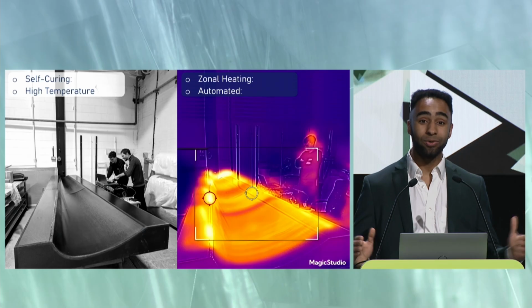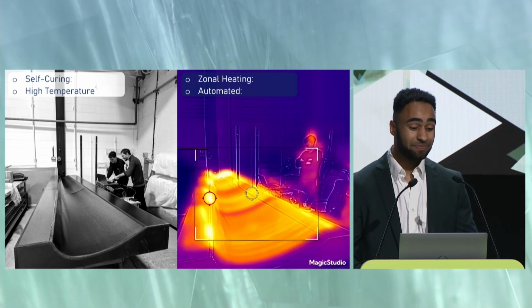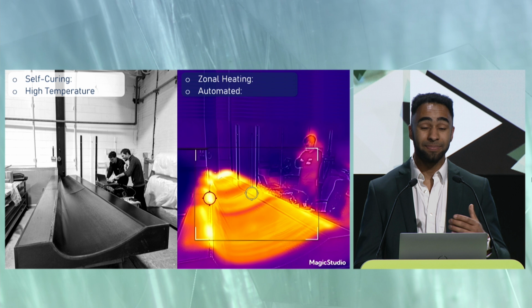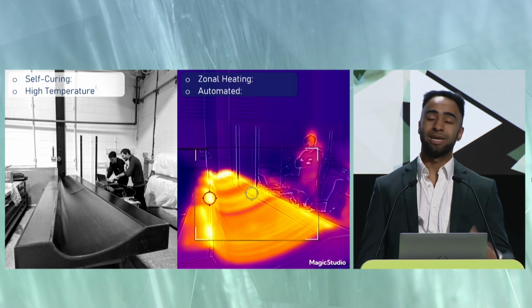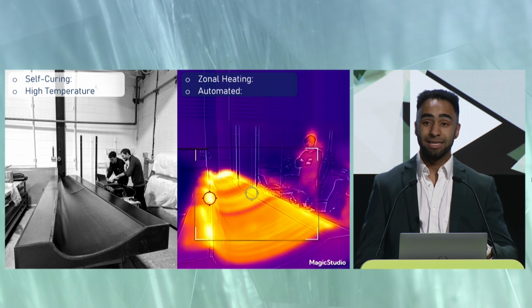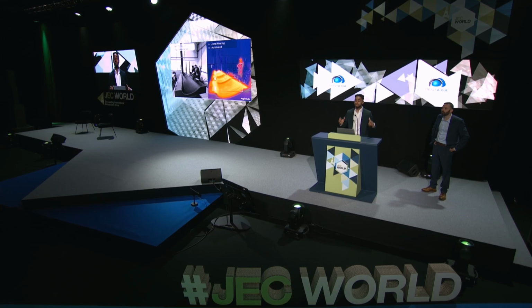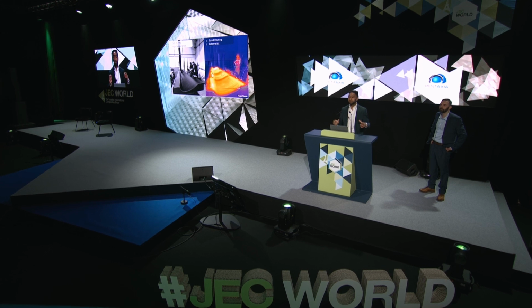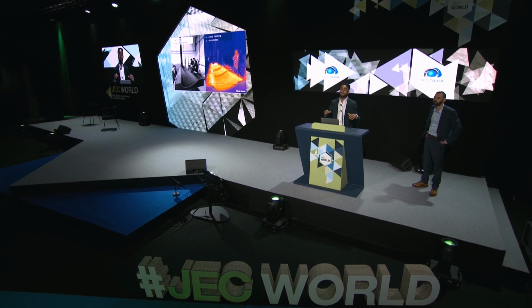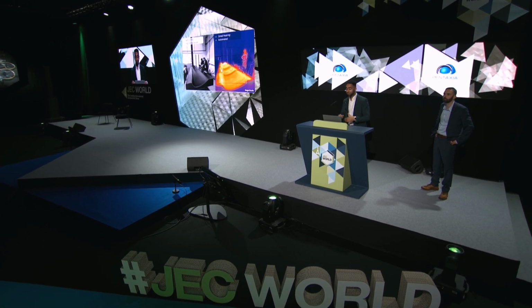So when we get the tooling heated up is where you really see the results that we've got. This entire project's been based around creating a 4-meter long wing skin tool for civil aerospace. And that's what you can see on the slide here. One of the really, really big novelties from this is that this tool here has actually been cured without ever seeing an oven or without ever seeing an autoclave. It's being cured directly on the pattern block under vacuum bag using the embedded heaters that are in the tool.